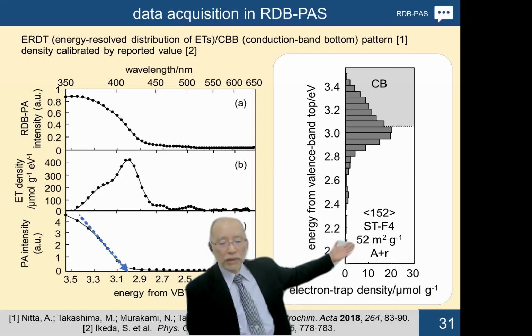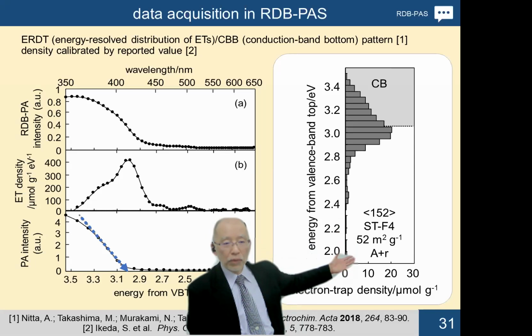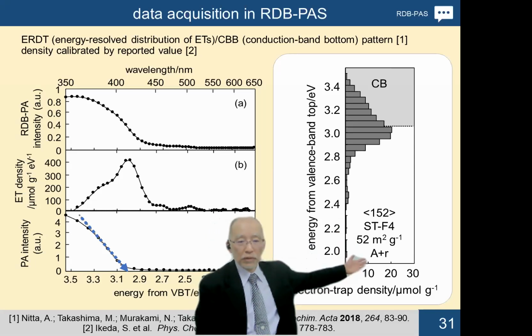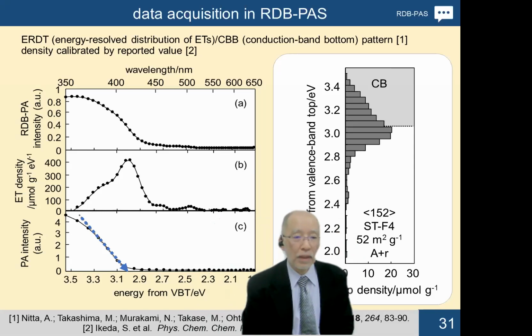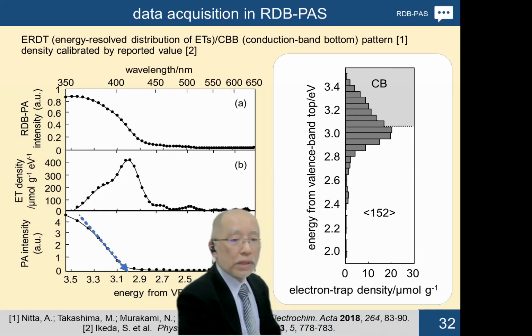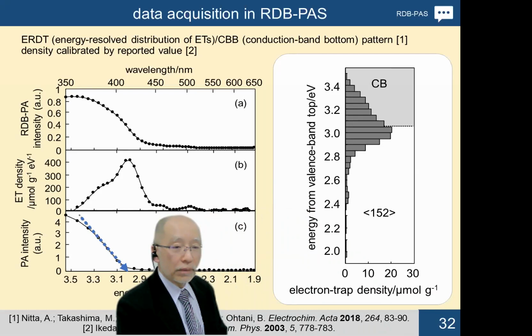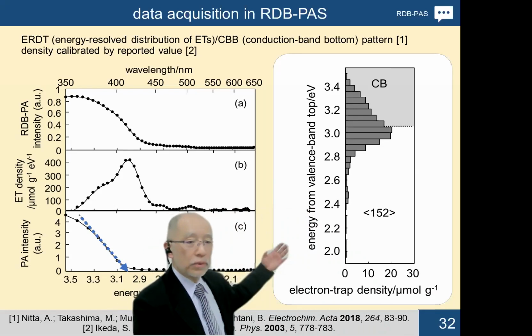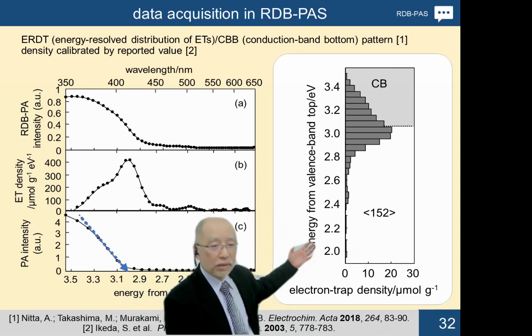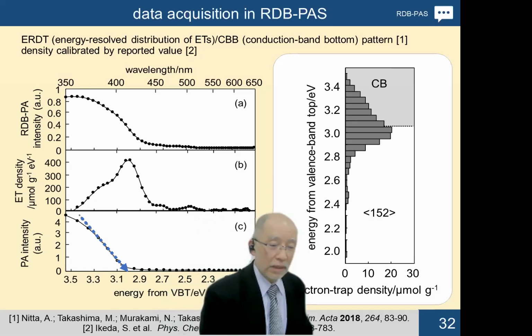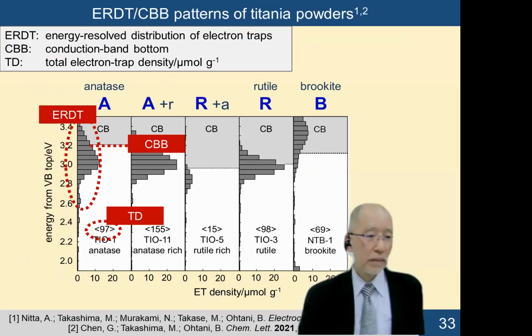And this is determined by conventional nitrogen adsorption measurement, a specific surface area of 52. And by using XRD technique, it is almost anatase structure, but a small amount of rutile is also included. But without using those conventional analytical methods, it is possible to show this is ST-F4 only by using this ERDT-CBB analysis. Then I will show you this.